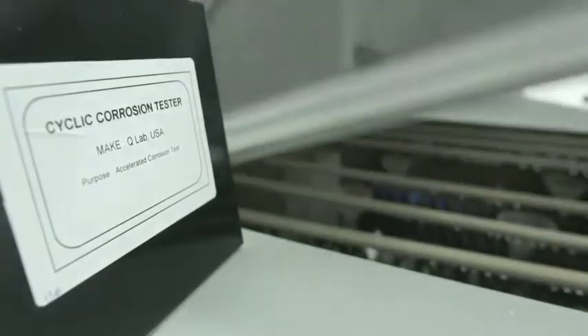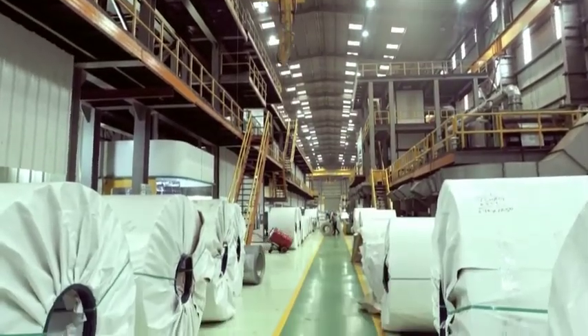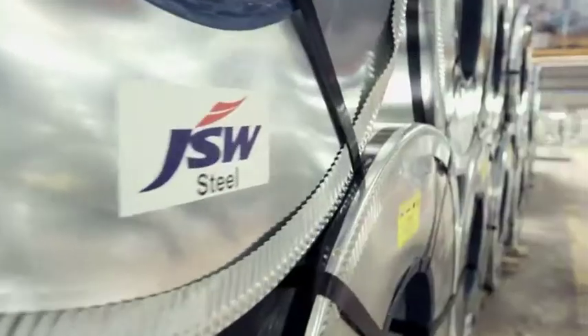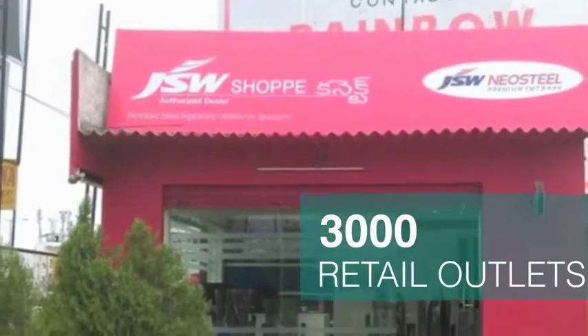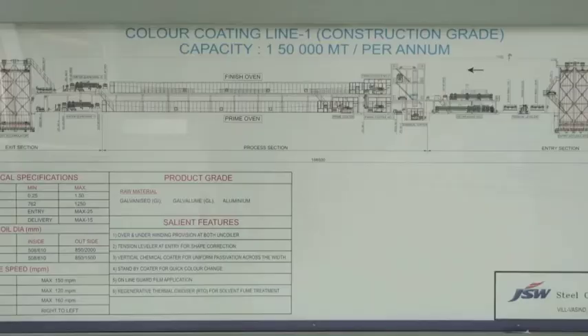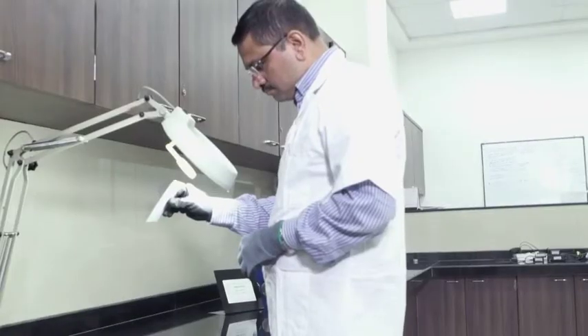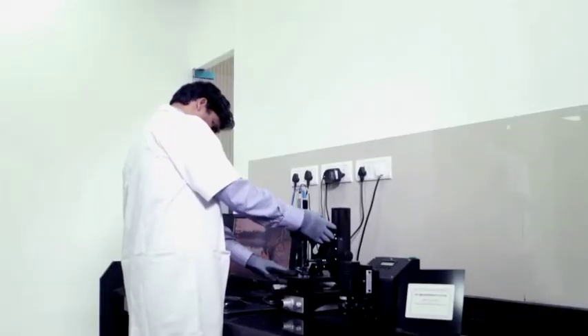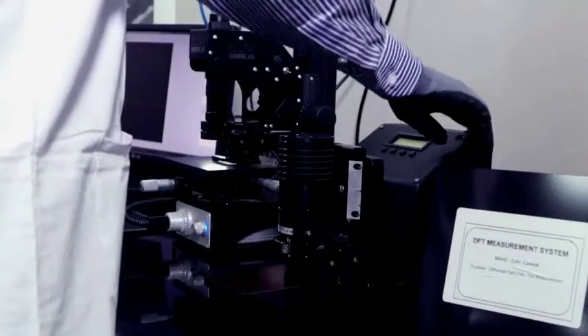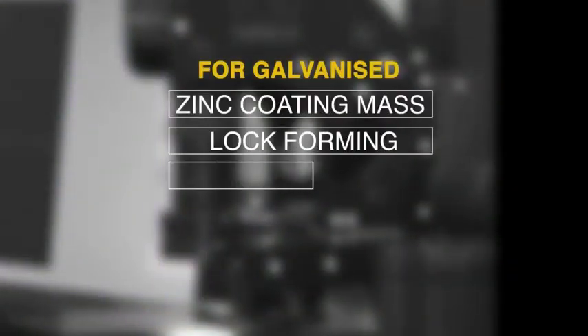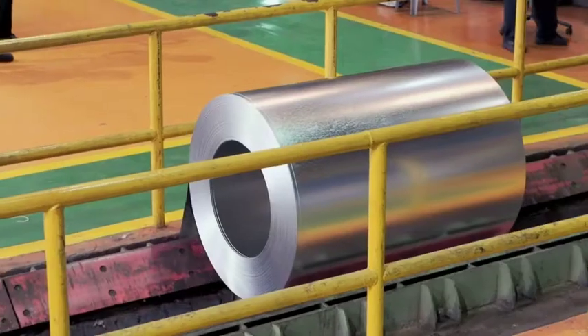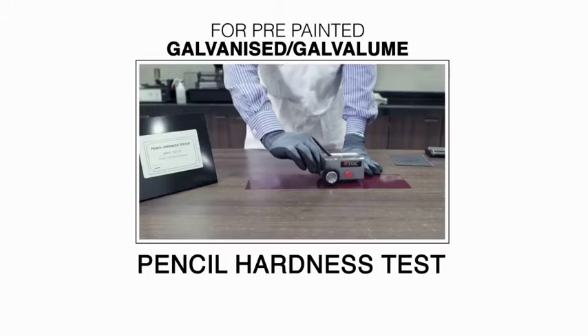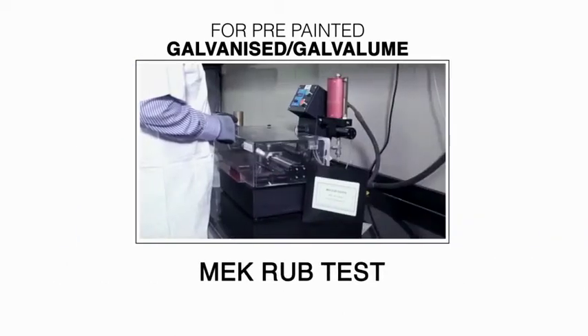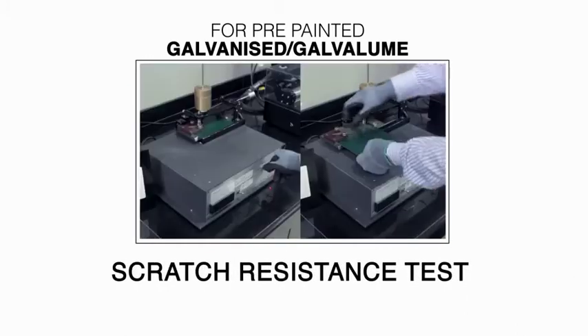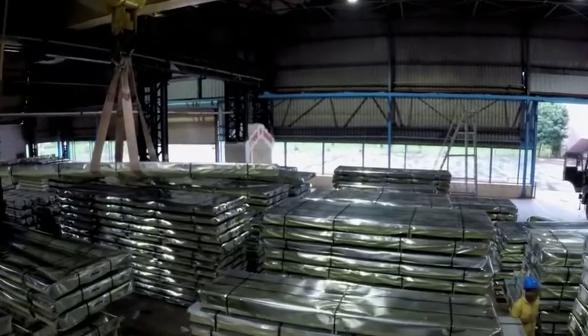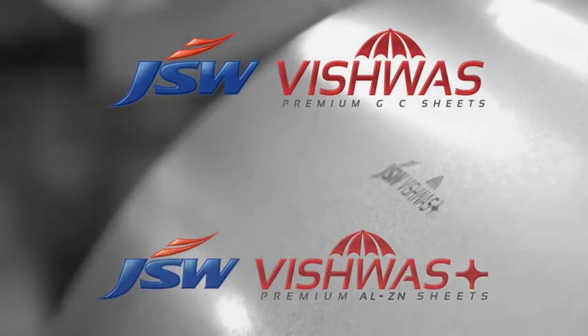The manufactured products undergo strict quality control checks to ensure absolute assurance. These galvanized products are certified by the Bureau of Indian Standards and are available in over 3,000 retail outlets across India. Before the products move on to the next stage of evolution, they are tested for quality in a state-of-the-art in-house testing facility. The finished product undergoes more than 20 tests before reaching the end consumer, including tests like, for galvanized, zinc coating mass, lock forming, hardness test, zero T bend test, tension test; for pre-painted galvanized and Galvalume, pencil hardness test, bend test, accelerated corrosion test, MEK rub test, dry film thickness measurement, scratch resistance test and more. The coated sheets are now ready to be shipped to the customer as JSW Vishwas or JSW Vishwas Plus.